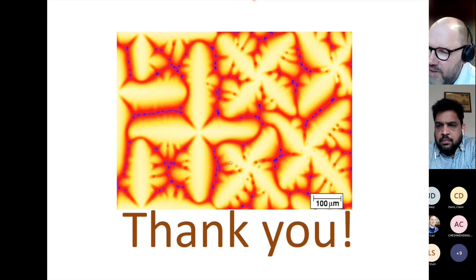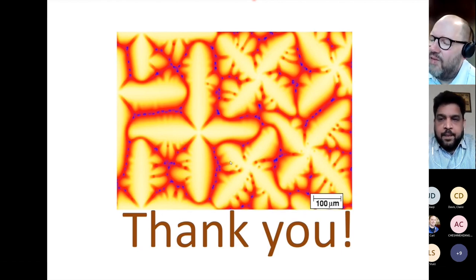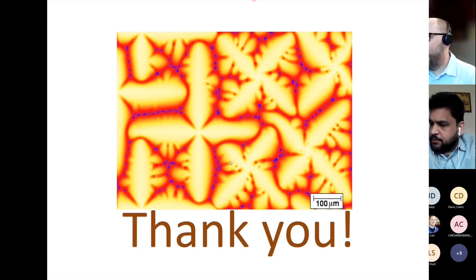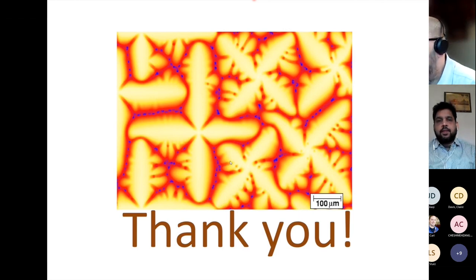But it needs to be kept in mind, and that's very important, that at a moving boundary between, let's say, the gamma and the gamma prime phase, that interface is still assumed to be in equilibrium locally. And that assumption is, for those very slow processes that I presented in the beginning, a rather good one. It works quite well. But it's an assumption that we force onto the system as well. Okay. Does that answer your question?